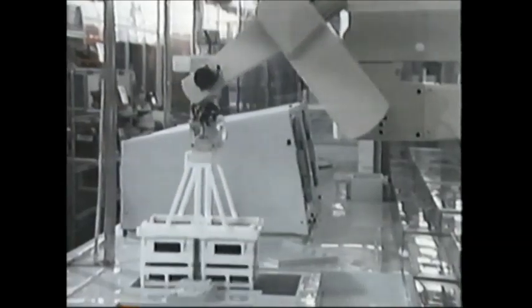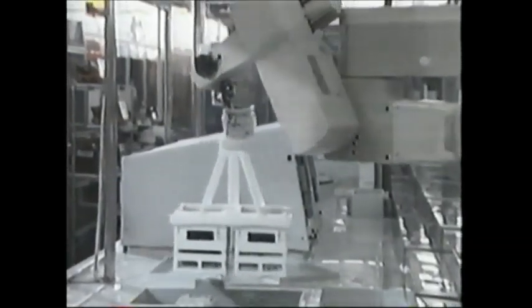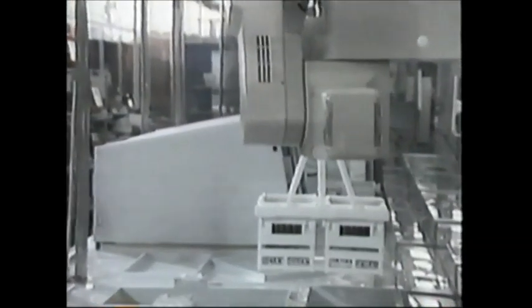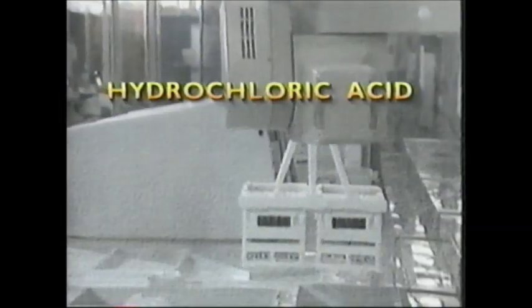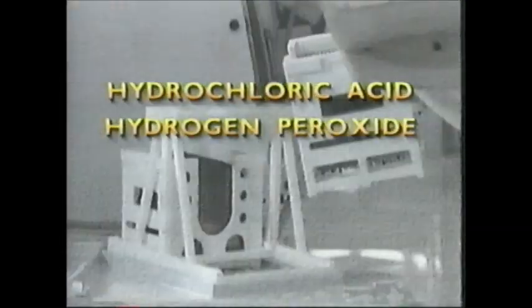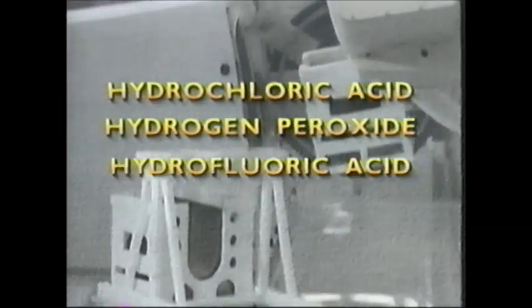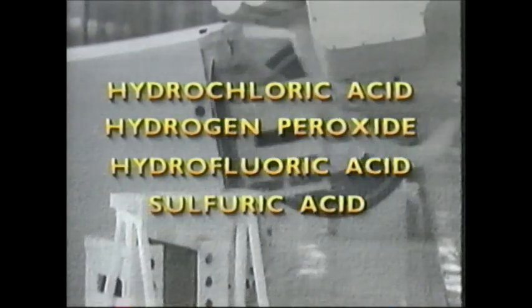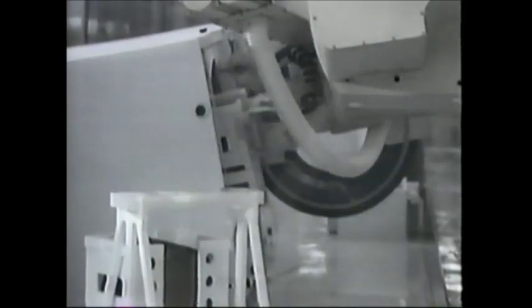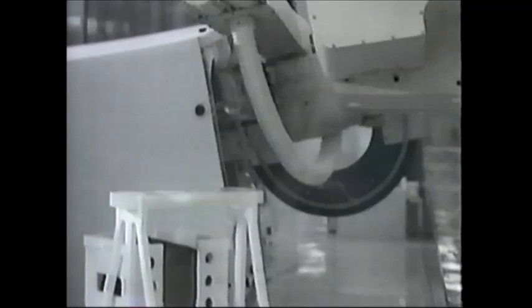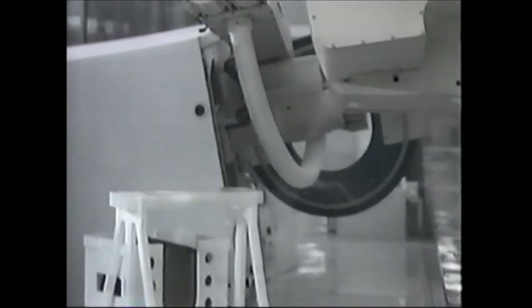Wafers must be cleaner than deionized water can make them, and to accomplish this, the wafers are bathed in solutions of chemicals such as hydrochloric acid, hydrogen peroxide, hydrofluoric acid, and sulfuric acid. These strong, corrosive liquids remove mineral and organic contaminants from the surface of the wafer.